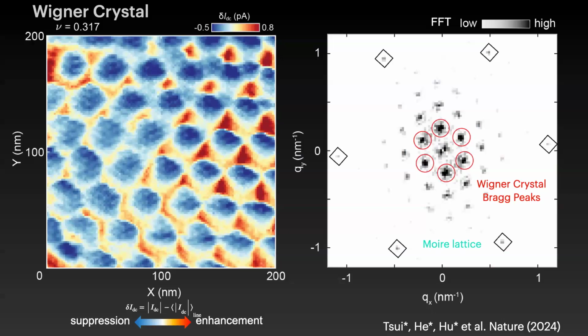So yes, this is our beloved Wigner crystal in a magnetic field. This is at this particular filling. You Fourier transform this data. You can see several features. You can see that these peaks out here are the Moiré lattice of the BN. There's no relationship between these. The lattice would rotate as a function of filling. This is one particular filling. And you can see the first order and second order Bragg peaks of the Wigner crystal.